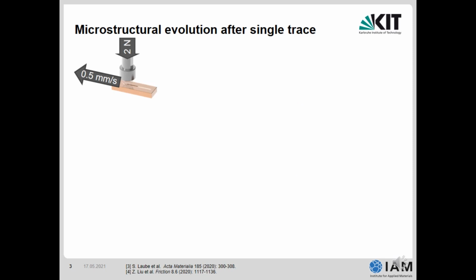So here you can see how it all started. First of all, we investigated polycrystalline copper. This was electropolished to achieve a defect-free surface. As counterbody, a sapphire sphere with a diameter of 10 mm was used. Furthermore, we have a normal load of 2 Newton and a sliding velocity of 0.5 mm per second.